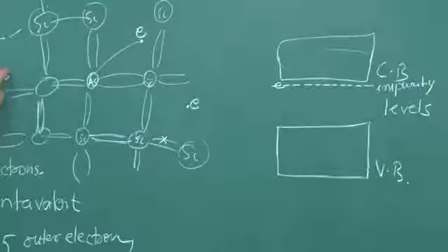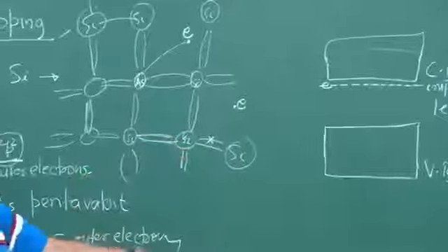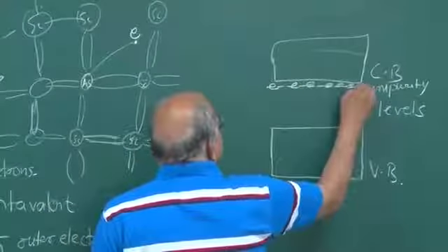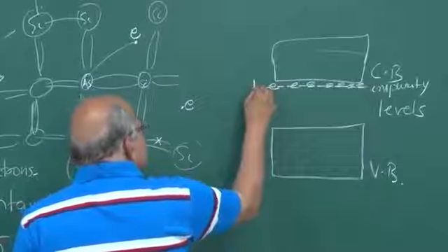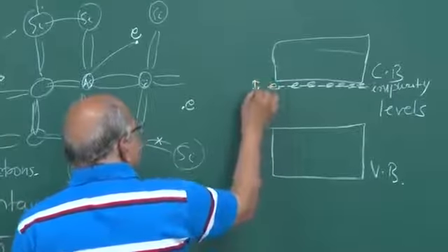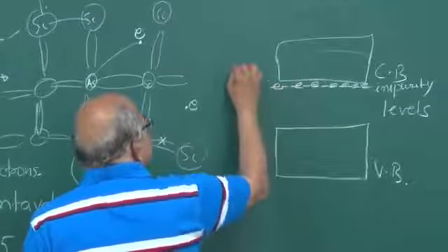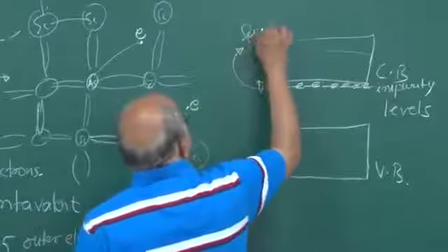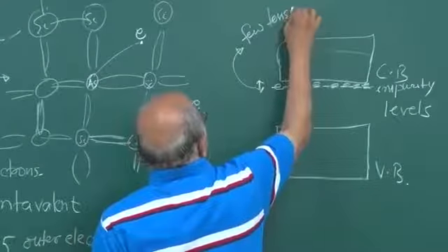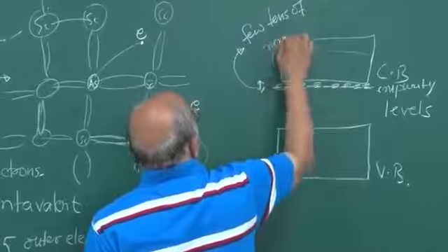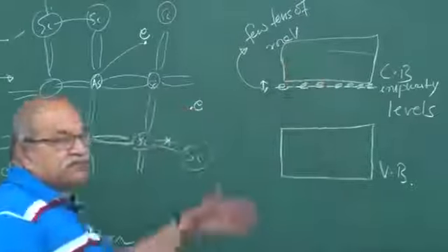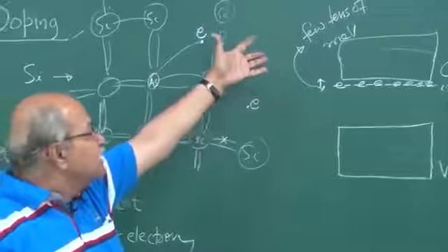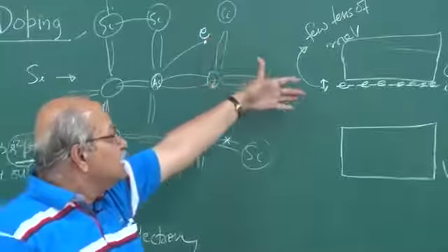So similarly you have arsenic here and there and there and there, and those electrons are in these impurity levels, and this gap here, this difference here is a few tens of milli-electron volts. Maybe 15, 20, 30, 40 milli-electron volts of this energy.